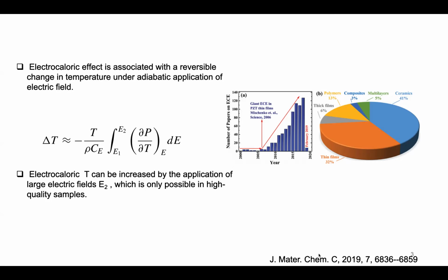So one of the ways to increase the change in the temperature is to apply a high field. That's what was tried in 2006 in the PZT thin films, where they were able to apply an electric field up to 776 kV/cm, and they were able to get a change in the temperature of around 12 Kelvin. After that, there has been an exponential increase in interest in materials to get a high change in the temperature in thin films.